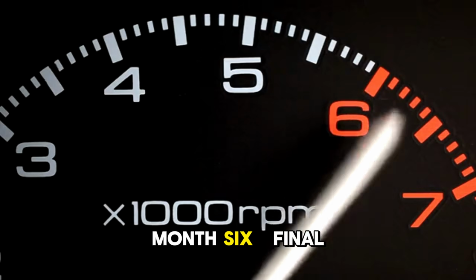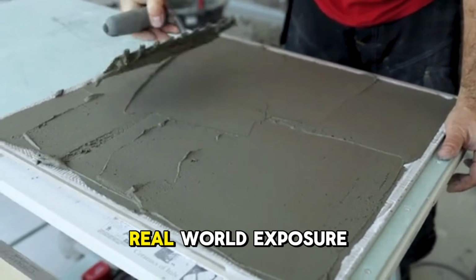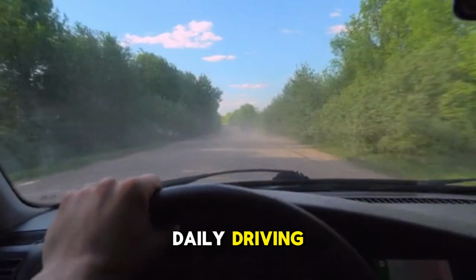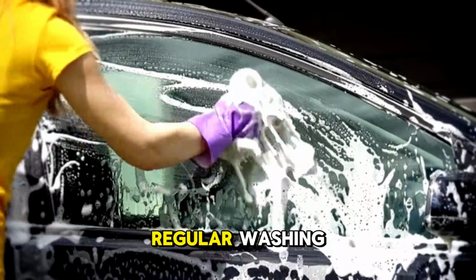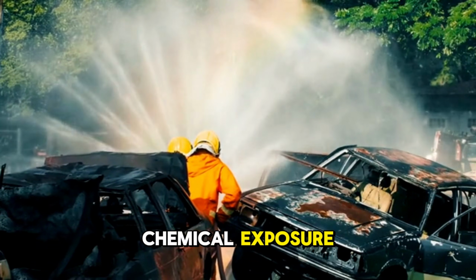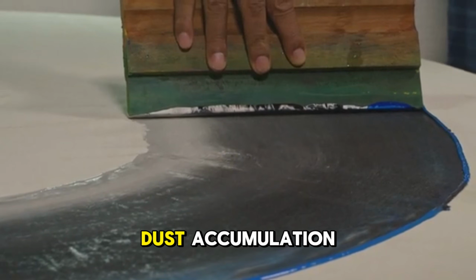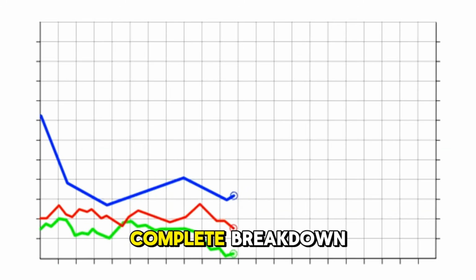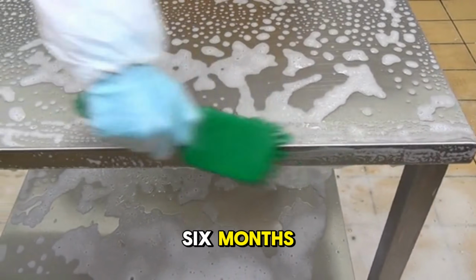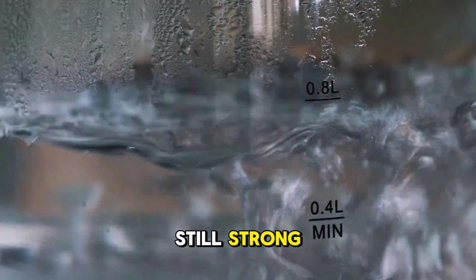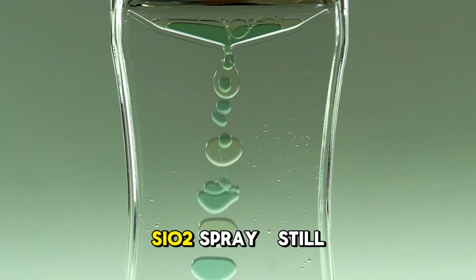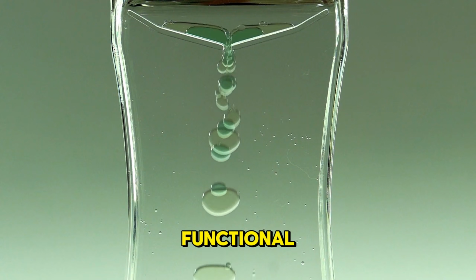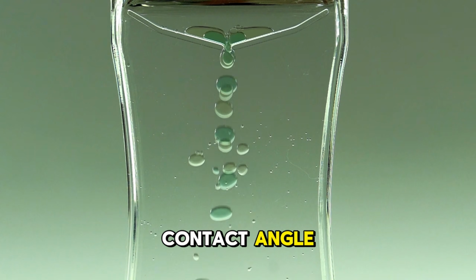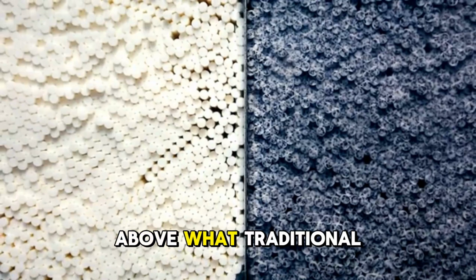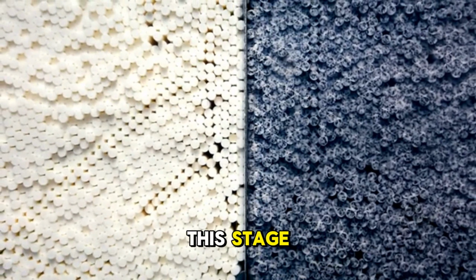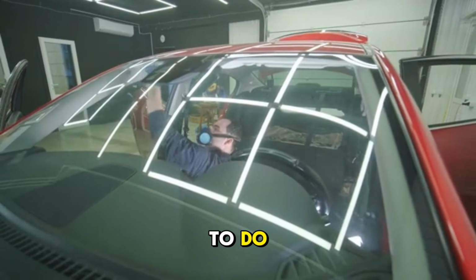Month 6. Final results. 6 months of real-world exposure. Daily driving, weather cycling, regular washing, chemical exposure, bird dropping events, dust accumulation. Here is the complete breakdown. Water beading at 6 months. Graphene coating, still strong, slight edge over SiO2. SiO2 spray still functional, marginally reduced bead contact angle. Both still performing above what traditional wax provides at this stage. Both still doing the job they were bought to do.